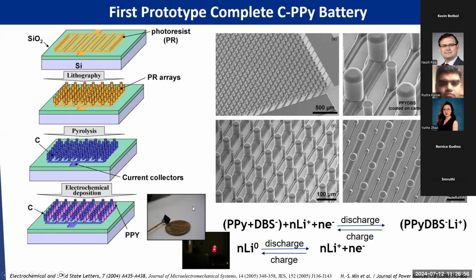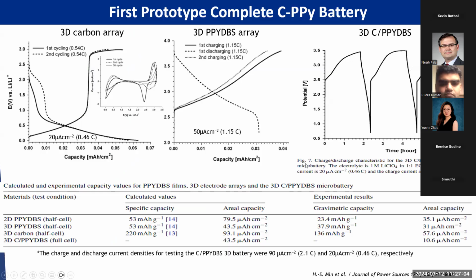So we adopt this polypyrrole and carbon as a first generation 3D micro battery structure. Then we did all these studies about the half cell performance and the full cell performance. And we found out this is not a good battery. Absolutely, if you look at the charge discharge curve, it's not like a typical battery.